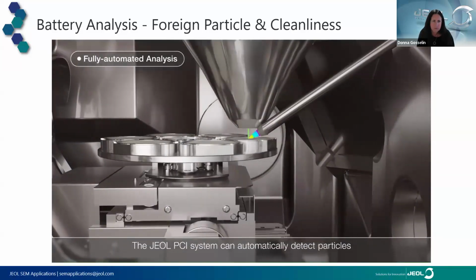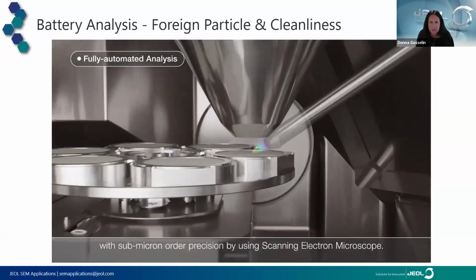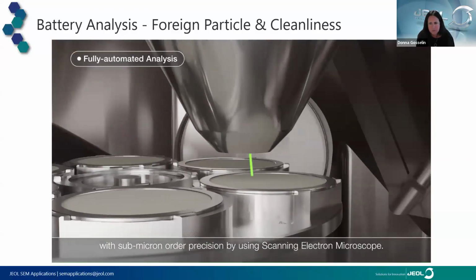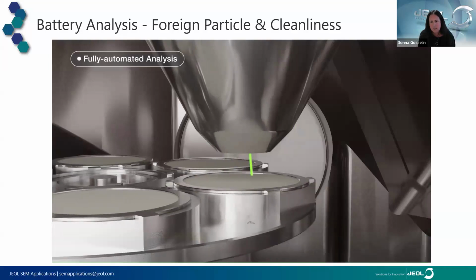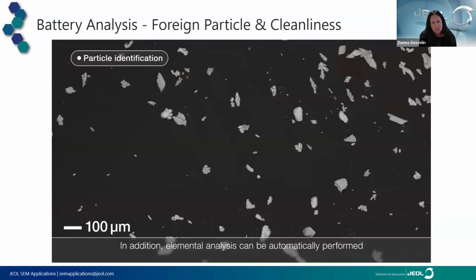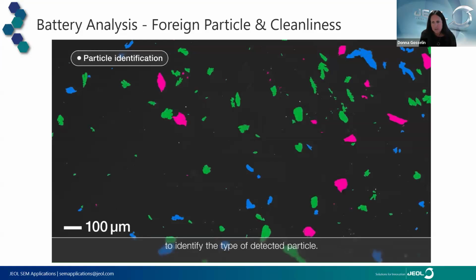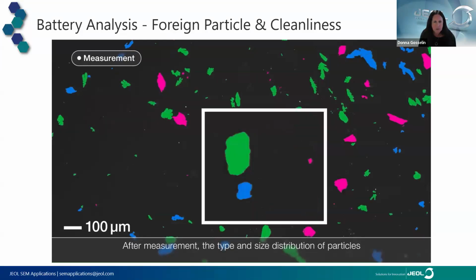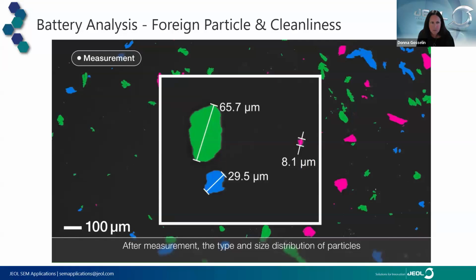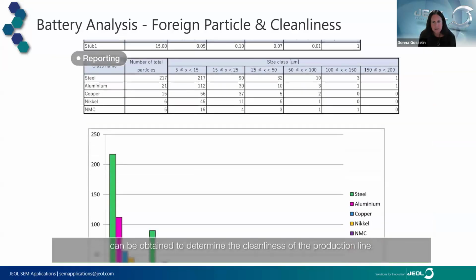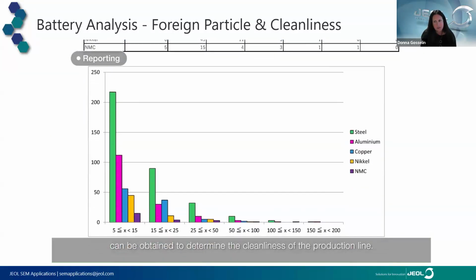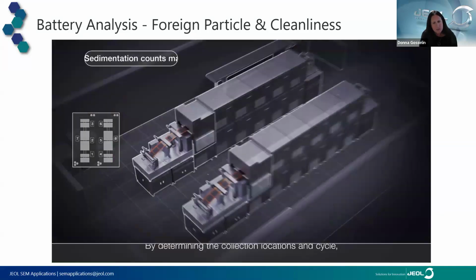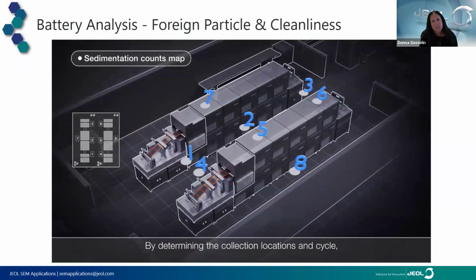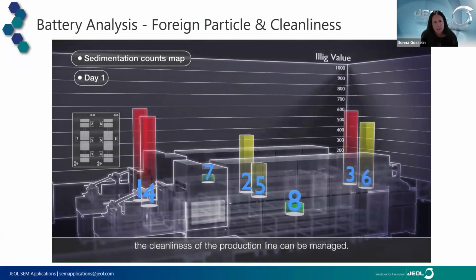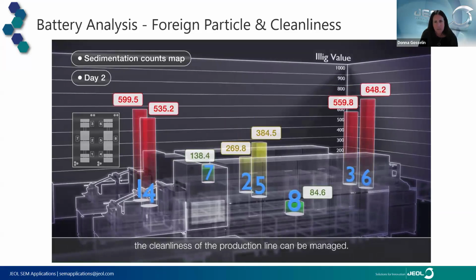Particles can be classified by chemical type, where the sediment is collected along the manufacturing line on filters. With JEOL's particle contamination inspection system, multiple samples can be placed in the SEM. We use the backscatter detector to threshold the particles based on their grayscale. And by detecting these particles, we can go back and analyze these automatically to get elemental composition. And recipes can be created for a quick and easy workflow, and the entire process can be fully automated within your lab.